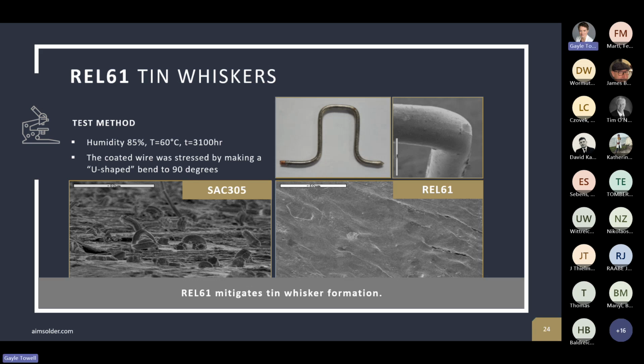And so we conducted a test, and under the test conditions with 85% humidity, 60 degrees Celsius for 3,100 hours, we had this coated wire that we bent, and we went to see if whiskers grew off of it. With the SAC305, we can see that there is tin whisker growth in this test. With REL61, there wasn't any.